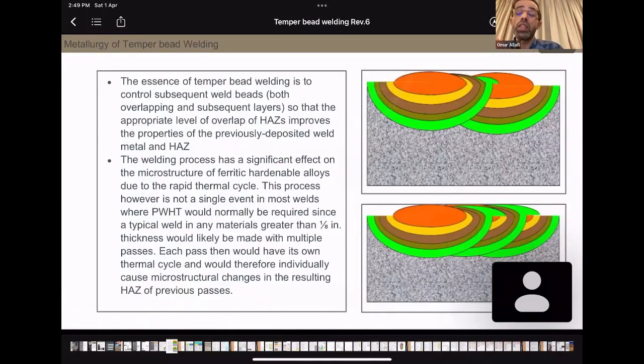So as I said, the essence of temper bead is to temper the previous weld by applying a new weld run. So you need an overlap. What we are doing is controlling some parameters when applying a weld run over a previous weld. So this new weld run will temper the previous weld and the heat affected zone as well. So mechanical properties will be restored, hardness will be reduced, and toughness will be within acceptable limits.